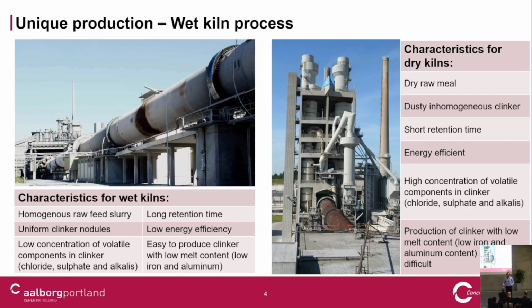So there's a benefit for the clinker, also because these raw materials already from the beginning form the nodule, the small balls in the kiln. It's easier to form the nodules in the wet kiln than in the dry kiln, meaning we can burn clinker with less iron content, less aluminum content - which are the materials that form the melt that creates the nodules. So in a wet kiln, it's easier to form a clinker with low C3A, with low iron content.